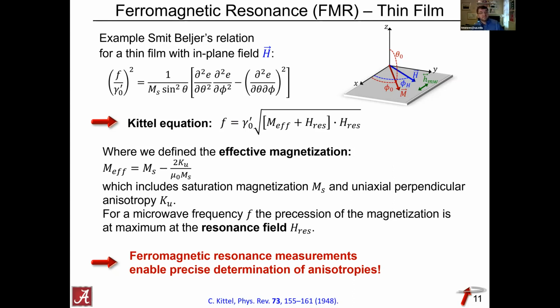There are a couple of things in ferromagnetic resonance. We cannot distinguish between the shape anisotropy and a perpendicular anisotropy, Ku here. So that's why we typically introduce what's called the effective magnetization, which includes both contributions. So you cannot separate those with a single FMR measurement. So over the years, ferromagnetic resonance has been used for quite a long time to precisely determine anisotropies. Question then is, so how do you actually measure that?